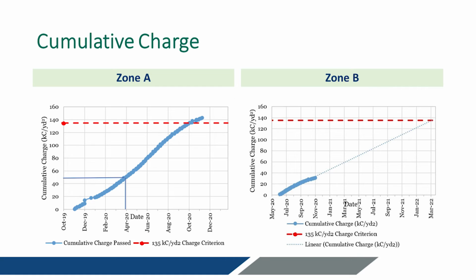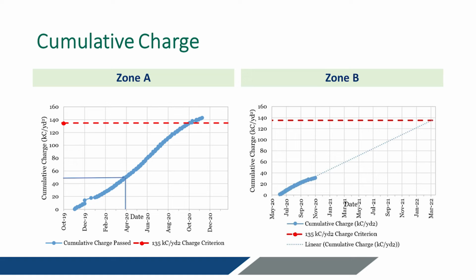So we see what charge, effectively the anodes are pushing electrons onto the steel, and so you can measure how much charge you're getting over time. Per the project specifications, the red dotted line was the criteria for reaching passivation. And so you can see based on the anodes that were installed in October, they reached that charge in about a year. And so here we have a zone that was installed in around May. And so, after a couple of months, it's still moving in the right direction. And in a little over a year, we'll reach that dotted line. And so we'll track that over time as we were tracking that as the project was going.